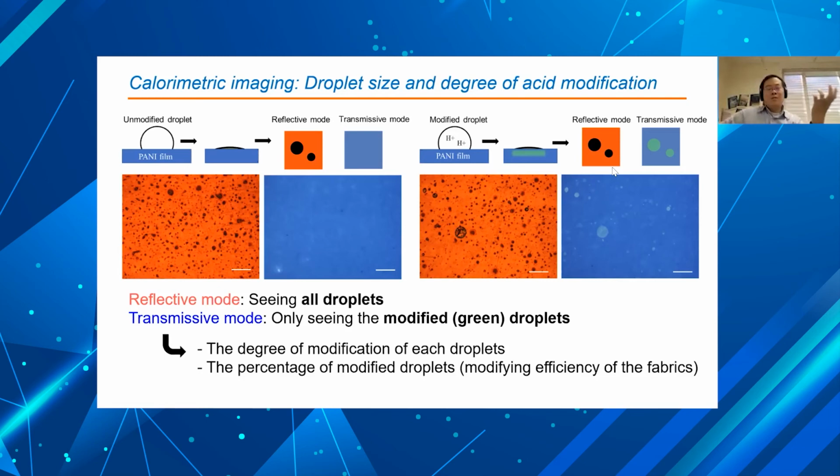So in our model droplets, we add in polymers and salt based on a standardized recipe. There are these model respiratory fluids out there. When this droplet lands on this detector screen, it dries up, and the dried respiratory mass deposits and changes the surface roughness of the film. So under reflective mode, they will scatter light more, so they will be less reflective, and they will appear as dark spots. So here is a reflectance mode image.